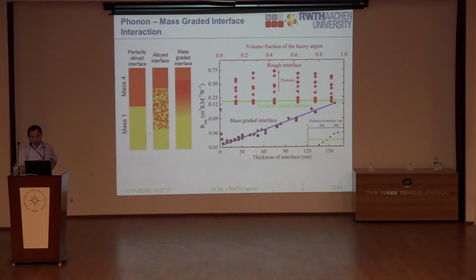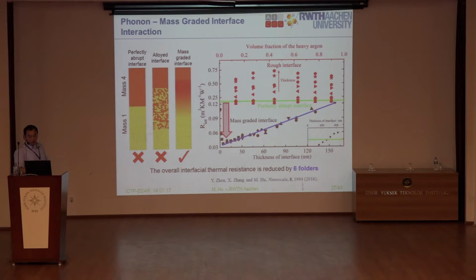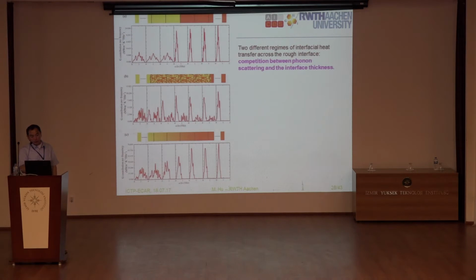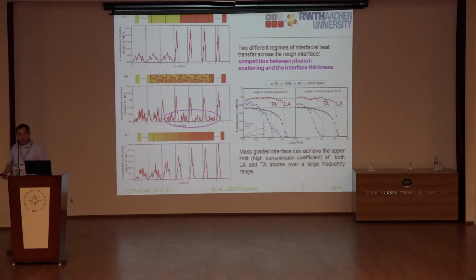Another example is to show the mass gradient interface, because sometimes you can make an alloy-like interface, and then you can also make the mass gradient interface. So we use a model structure, and then we found that if you use a mass gradient interface, the thermal resistance can be reduced by 6 fold. So this is also a similar mechanism, and then you can use some method to analyze the mechanism.